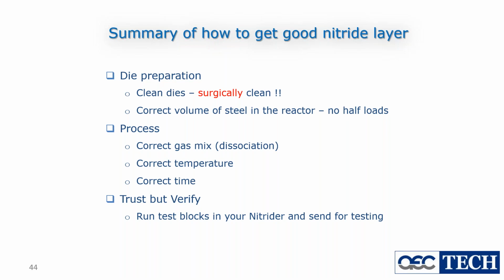Okay, the correct volume of steel in the reactor, because these reactors are designed to be full, and the programs have been designed to give the service to a full reactor, not half loads. And process: correct gas mix to have a dissociation, correct temperature, correct time. It all matters. And then at the end, you have to trust but verify. What that means is you have to run test blocks in your nitrider and send those test blocks for testing to make sure that you get a nice hardness profile and your indenter makes clean indentations.